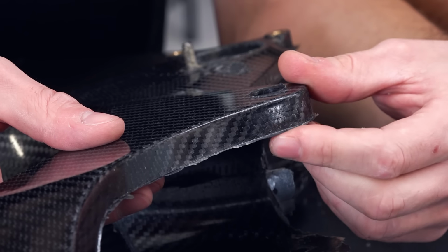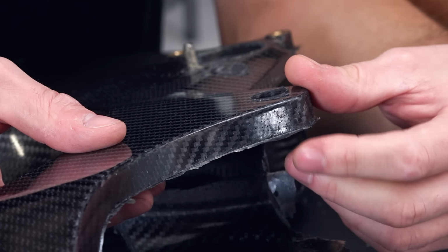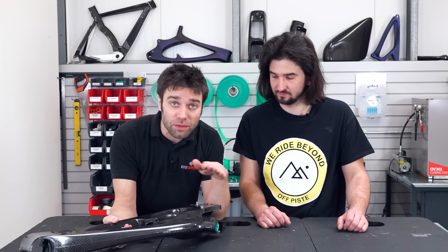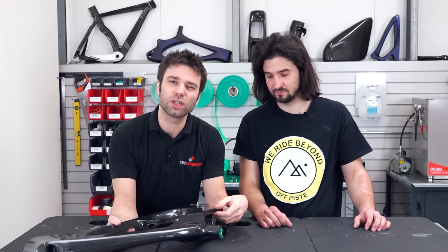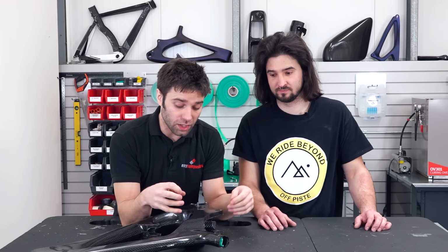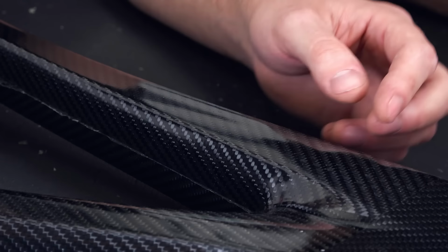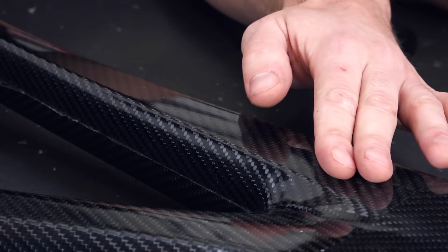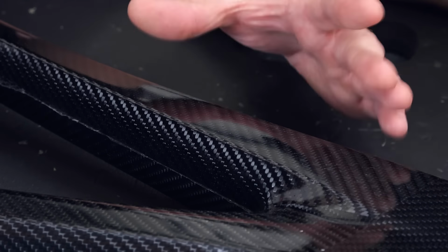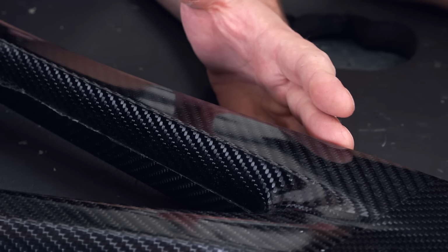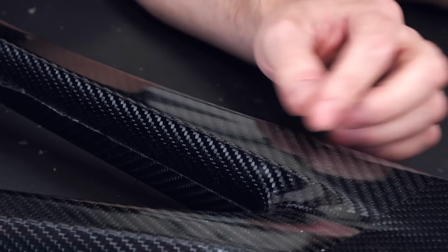So looking at this, you can see we've got quite a bit of flash. There's the occasional bit where the odd fibre has come out into the flash line. That's what you're trying to avoid when you close the mould. But as long as you only get very slight bits, single fibres, they will get clamped into the mould and won't cause a problem. So if we get up really closely to this top tube section here, you can see the end result that we've managed to achieve straight from the mould. Now, there are some very, very small surface pinholes here.